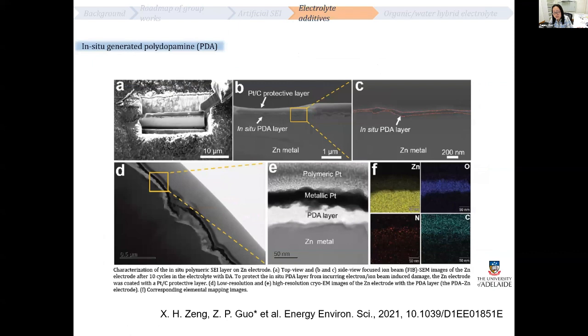So we try to see the thickness of the in situ SEI layer, but because the surface is quite soft, we applied a platinum carbon protective layer and used focused ion beam to cut the surface. And from the cross-section view, we can see the thickness of this in situ SEI is around 40 nanometers. It's thinner compared to the inorganic SEI.